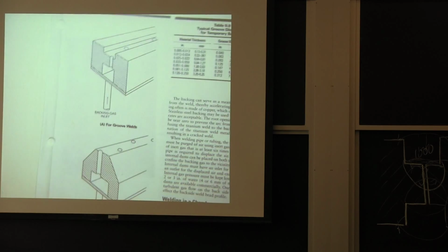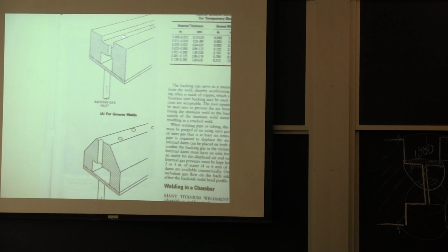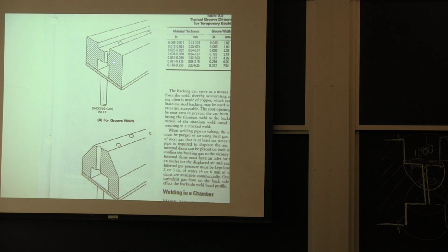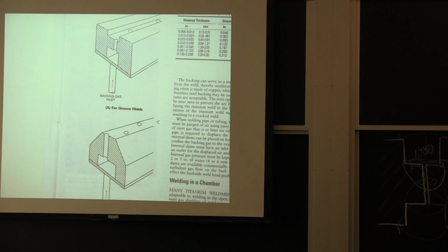You may have welding, but you have all kinds of purging things. You might put a plate across here. You put this up against the weld, and you have a diffuser. You bring in backing gas, they call it backing gas. You bring in your high purity argon, you diffuse it in here, it fills it and floods the area. I mean, you might end up using 10 times as much shielding gas when welding titanium.